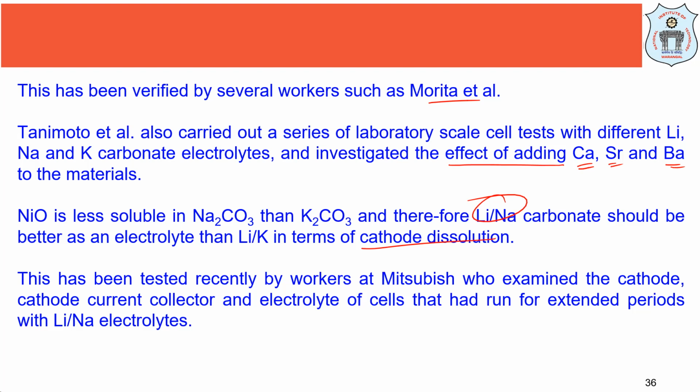So they added a certain percentage of them, and studied how it suppresses the cathode material solubility in the solution also. Okay, so nickel oxide is less soluble in sodium carbonate than potassium carbonate, and therefore lithium sodium carbonate should be better as an electrolyte than lithium potassium in terms of cathode dissolution. Okay, so that problem is taken care of when you use lithium sodium carbonate rather than other combinations.